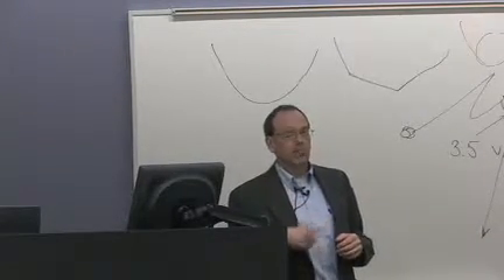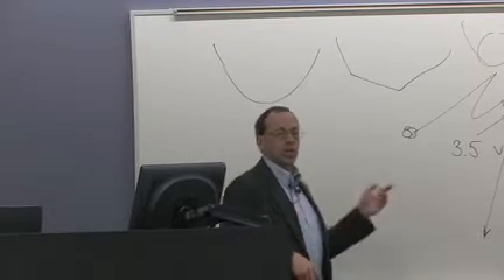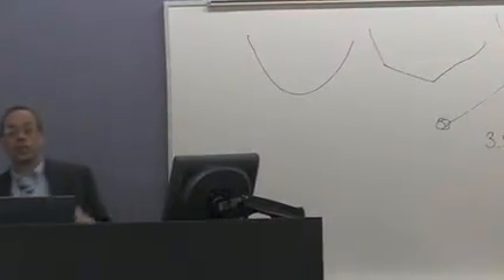There is a lifetime as to how long you can repeat that process. We believe it's around 50 times. We've certainly had cases where we test them in the lab, 50 consecutive builds in a row. If they typically last a week, that's a year's worth of rebuilding. When the instrument's in the field, I think we typically say there's a 6-month expected lifetime to the tip before we replace it. But in practice, it gets replaced because of some other reason. They want to do an experiment, for example. So it's not uncommon to have 6 months to a year as a typical lifetime of an emitter.